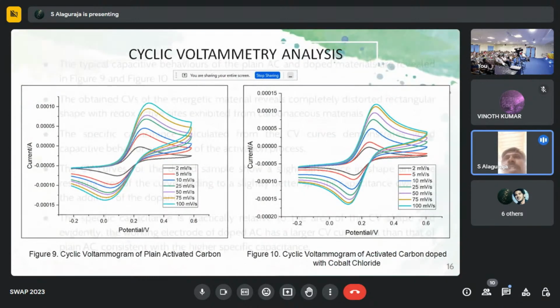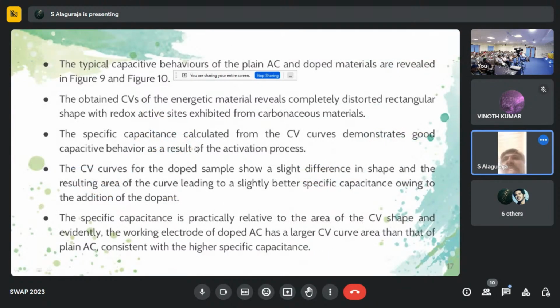From the CV cyclic voltammetry analysis, the specific capacitance calculated from the CV curves demonstrated good capacitive behavior as a result of the activation process. The CV curves for doped samples show a slight difference in shape and area, leading to slightly better specific capacitance owing to the addition of the dopants. The specific capacitance is proportional to the area of the CV curve, and evidently the working electrode of doped AC, where AC means activated carbon, has a larger CV curve area than the plain activated carbon, consistent with the higher specific capacitance.